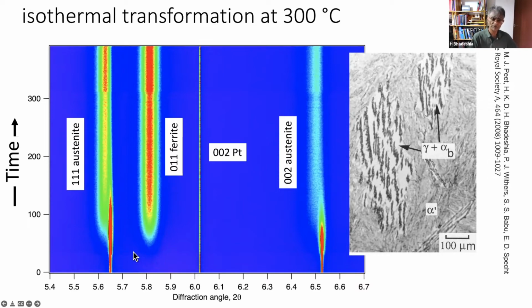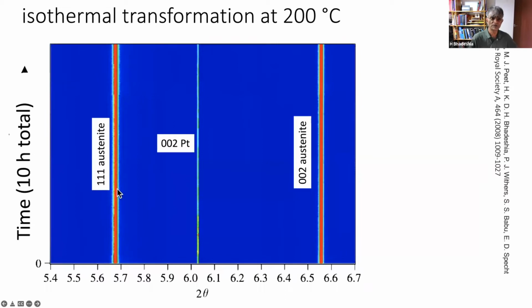And I'll show you another experiment where we have much longer time before transformation starts at 200 degrees centigrade. And absolutely nothing happens to the austenite before transformation. This is the platinum reference so that we can calculate instrumental broadening and various other things. So you can completely rule out, even at a low temperature of 200 degrees centigrade, that the austenite splits into composition-rich and composition-poor regions, and that the bainite forms in the carbon-depleted regions.